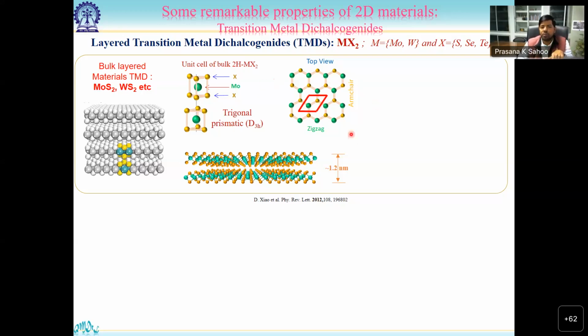From the top view, it looks like graphene. Instead of carbon, it has alternating molybdenum and sulfur or selenium atoms. They form hexagonal rings. A unit cell thickness is just 1.2 nanometers, and a single layer is just 0.6, about half a nanometer. That's why a half-nanometer semiconductor gives very extraordinary properties.